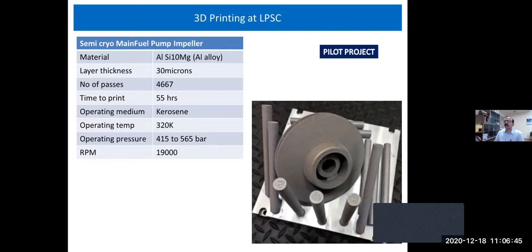And then this is another impeller, again printed with aluminum alloy. Don't get confused, the part in the middle is the aluminum alloy. And as I was telling, for characterization, along with the build, we will have to build coupons. These are all the coupons built in different orientations. You have coupons built in the x-axis, in the y-axis, in the z-axis, and also at 45 degrees. So you have to get the properties at all different orientations.